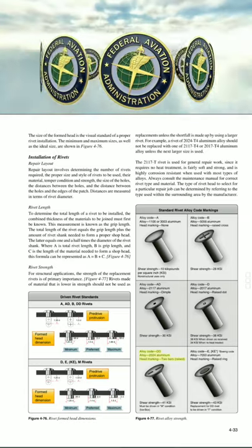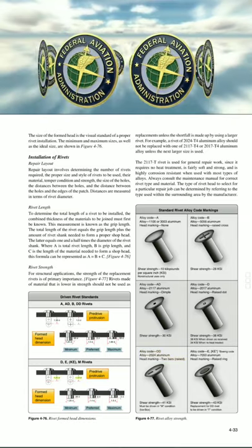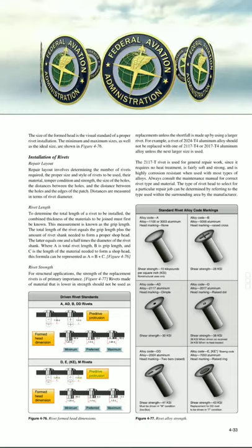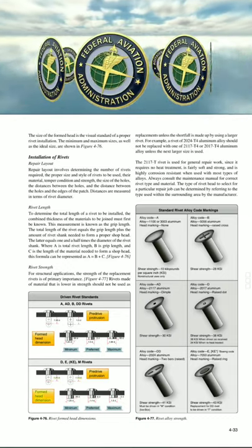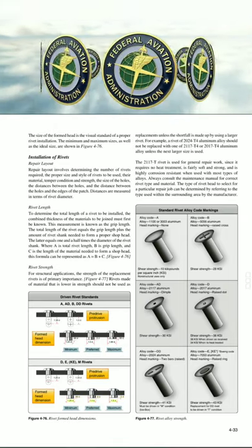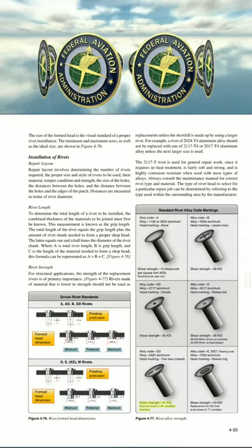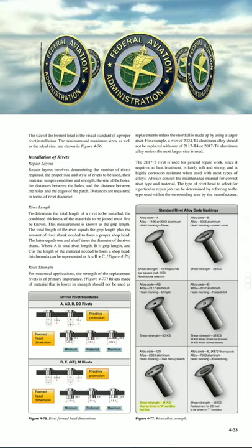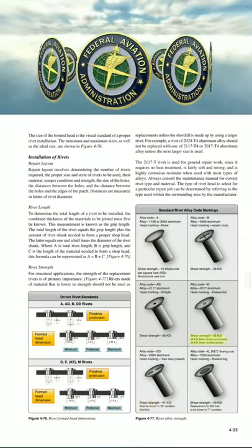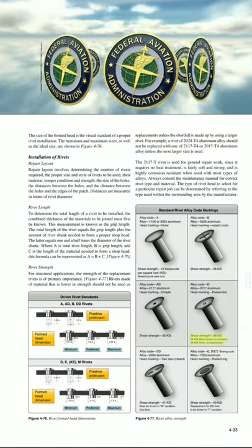Alloy code DD, alloy 2024 aluminum, head marking 2 bars, raised. 1.25D, 1.33D. Predrive protrusion. Formed head dimension. 0.66D, 0.6D, 0.5D. 1.25D, 1.4D, 1.5D. Minimum, preferred, maximum. Shear strength 41 KSI, must be driven in W condition, icebox. Shear strength 38 KSI when driven as received, 34 KSI when reheat treated.